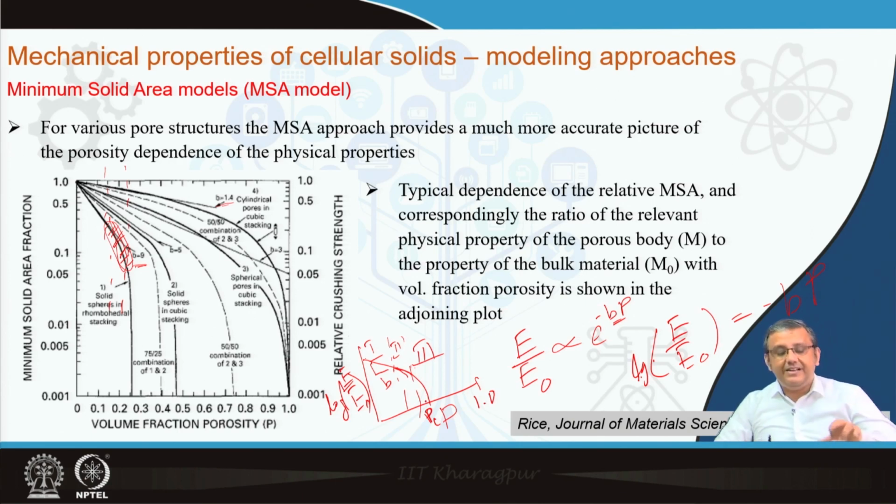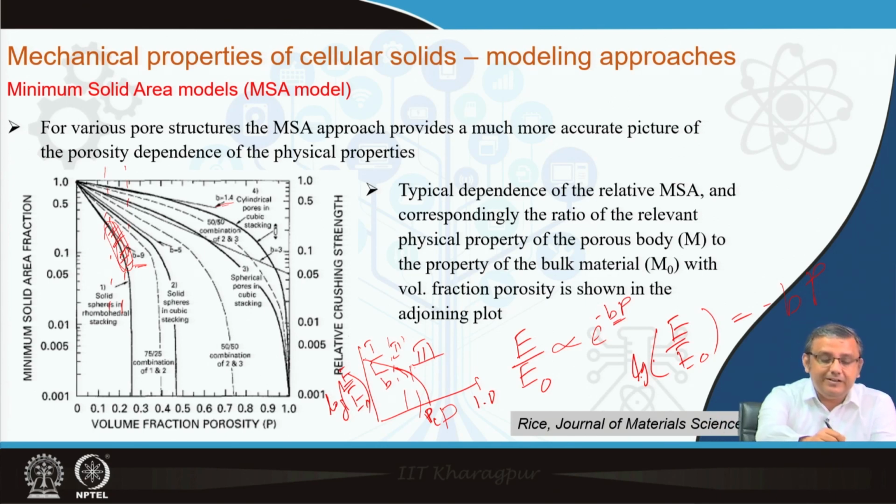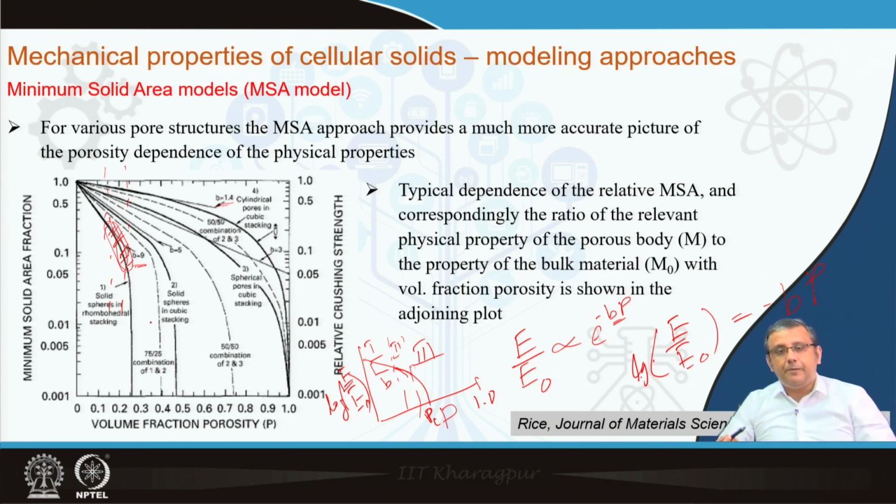And also these models have been very successful, because if we try to find out the properties of real porous materials over a range of porosities, we actually end up with this kind of a curve, where above the critical porosity of PC we also obtain an almost 0 property value, and these things will be discussed in much more detail in the coming lectures.